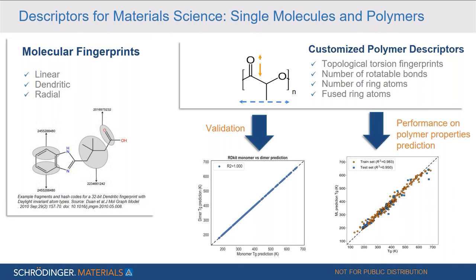And what we can also see here in the validation example plot down on the bottom of the page, the predicted Tg is plotted for the monomer versus the dimer representation in order to make sure that both give the same results. So if we define the polymer in the dimer representation and in the monomer representation, we should end up with the same results because still it is the same homopolymer.